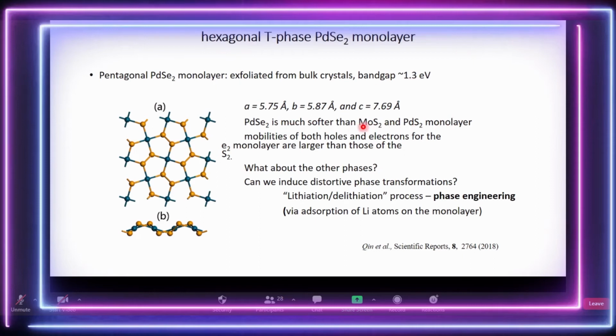This is softer than other monolayers, MoS2 or PdS2, and mobility is also pretty high. So coming from the graphene point of view, as we know, boron nitride and graphene have a hexagonal structure. So the idea is we move from pentagonal to hexagonal structure: what kind of properties is this material going to have, and can we use it to make heterojunctions, which I'll come to a little later. Now, there's a route where you can go from pentagonal to hexagonal phase by high pressure phase transition, but then it is going to be metastable. And for applications, we need stability at ambient conditions.